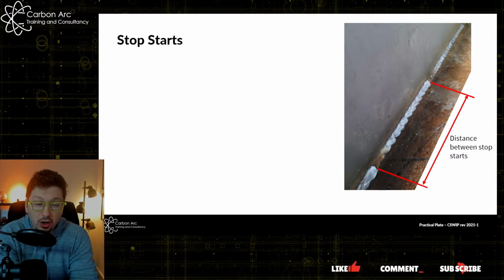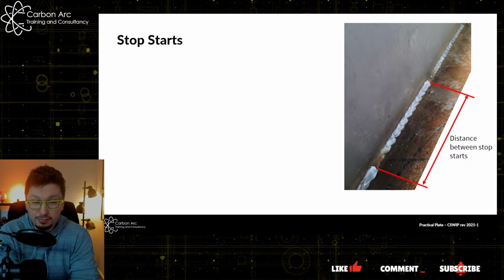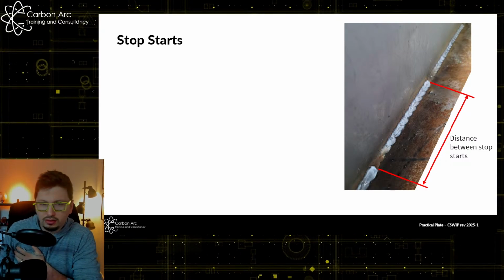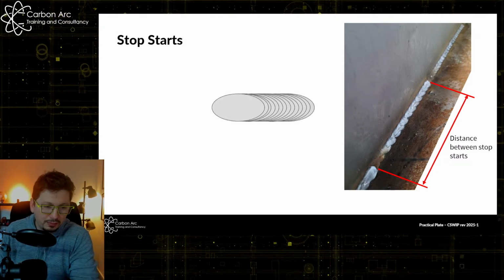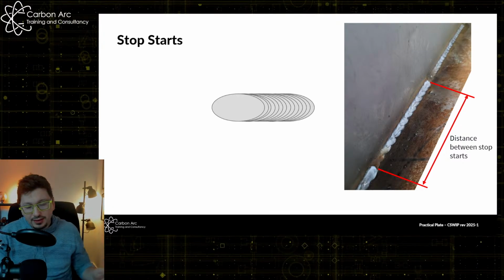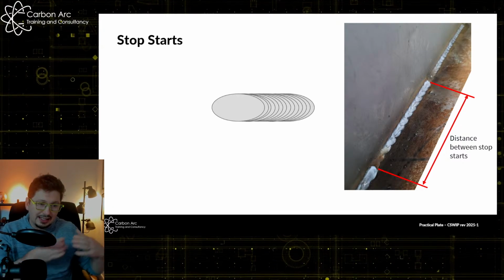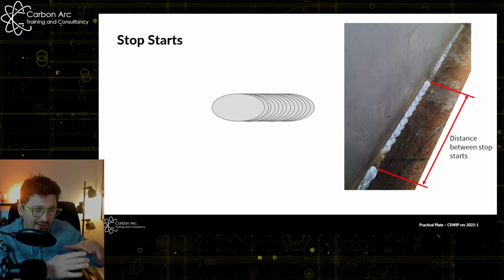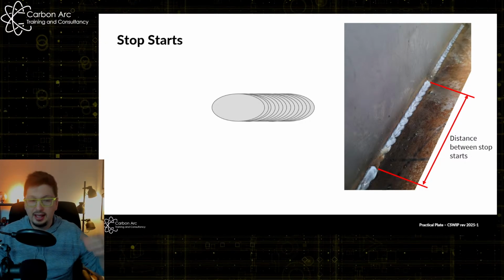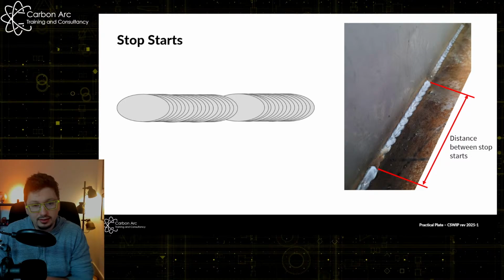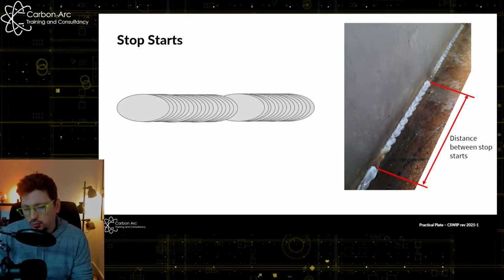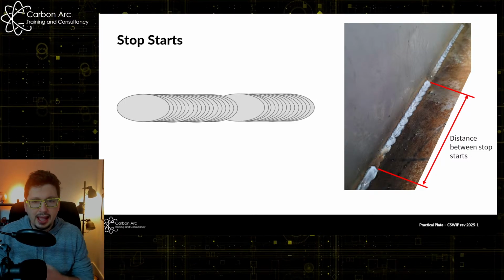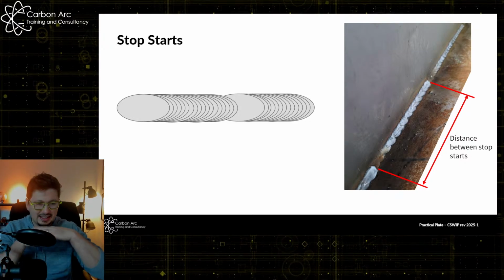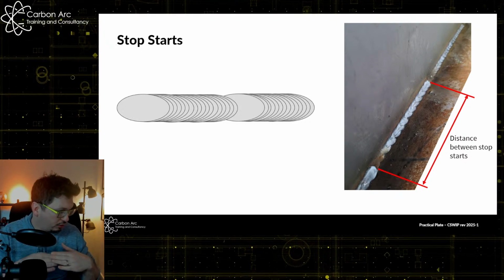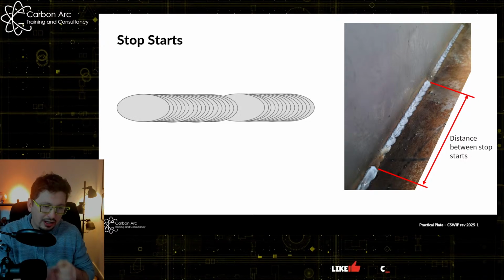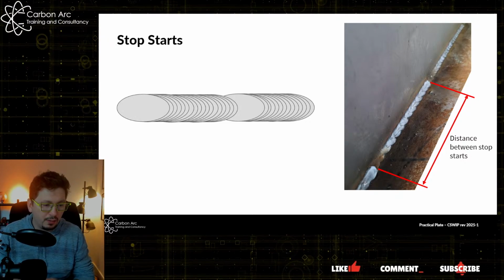And really what we're looking for is these poor stop starts. Okay, so I've tried to draw this out, so bear with me. So we've been welding along, and then we stop, and at the end of the weld we have that flat crater position, and then we restart to weld, and we come along, and we end up with something like this. Anywhere where we can see that overlap of the weld and that crater in the middle is going to be our poor stop start.